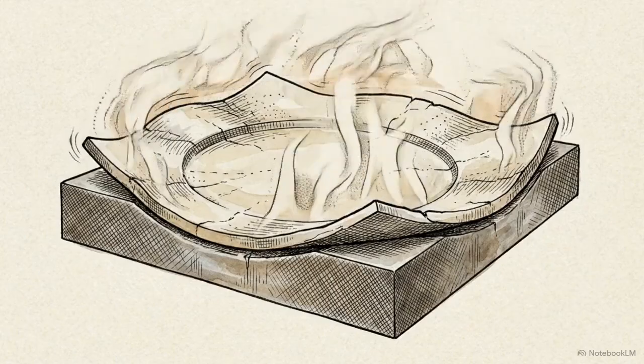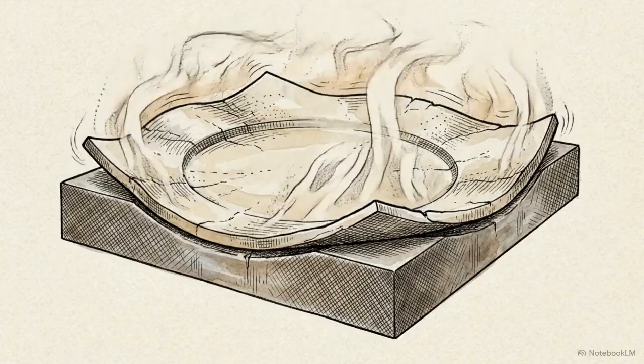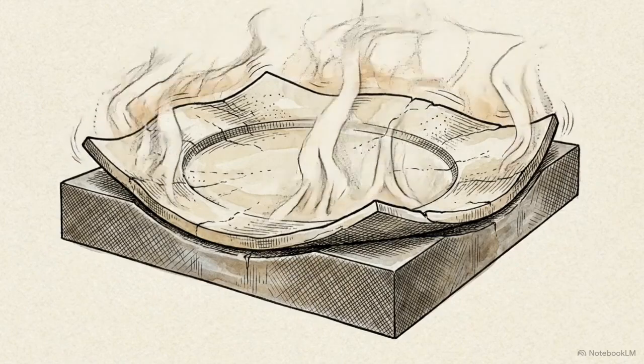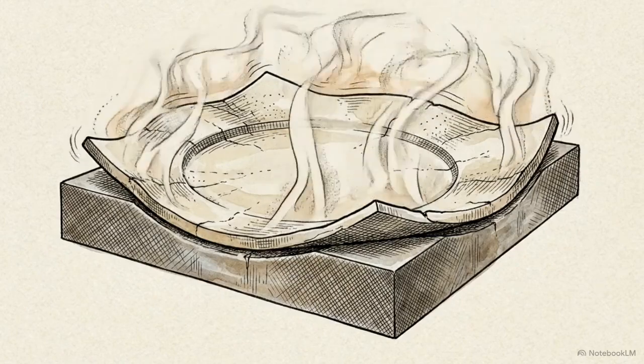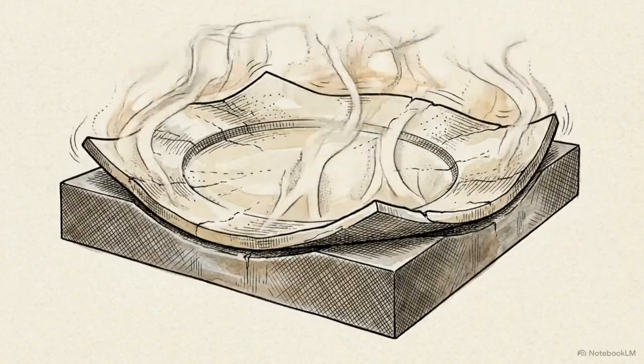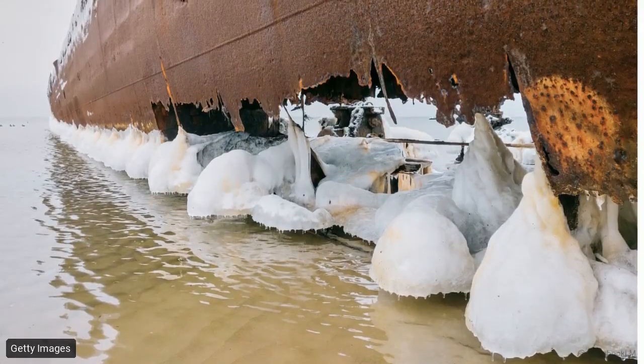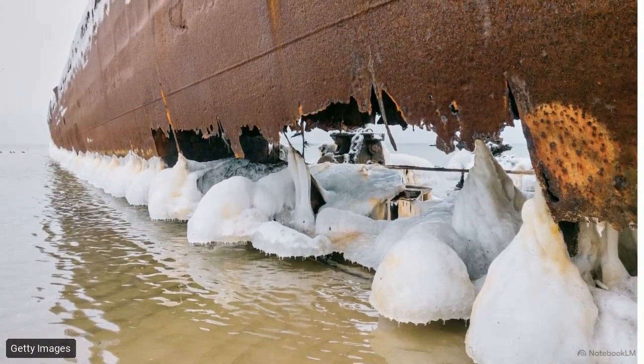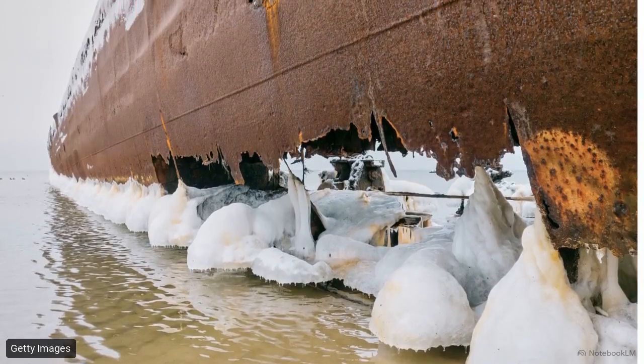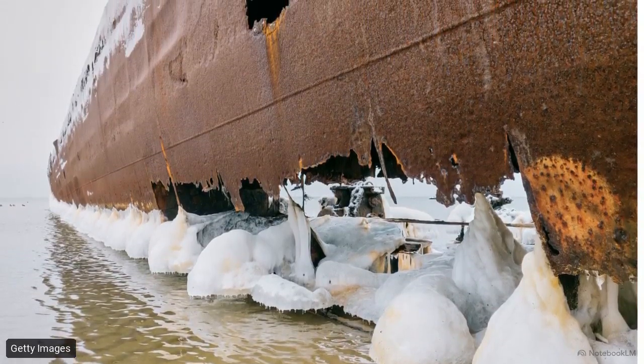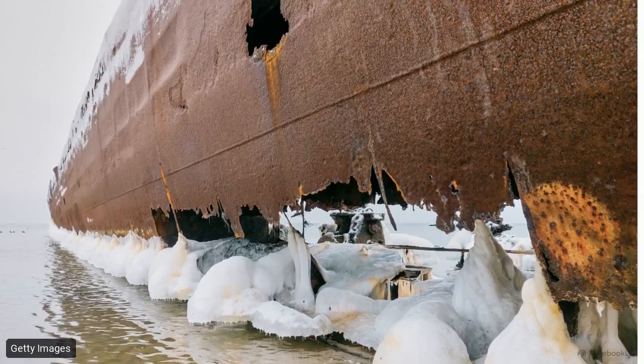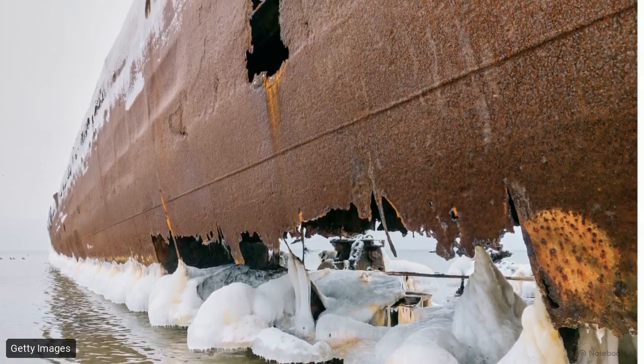This creates a direct engineering conflict. Heat required to build the ceramic's thermal stability simultaneously threatens its mechanical adhesion to the surface. In harsh environments, this microcracking leads to failure. Marine corrosion targets these microscopic defects to accelerate structural degradation and deep pitting on metal surfaces.